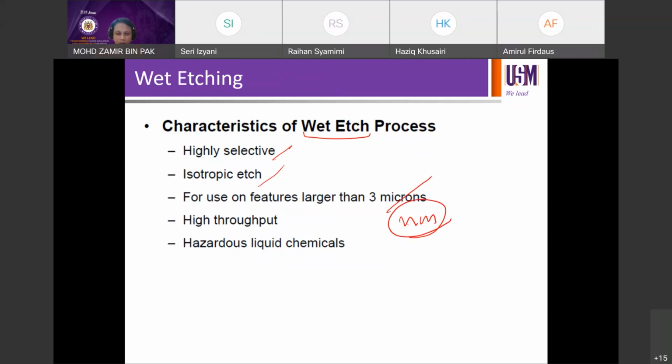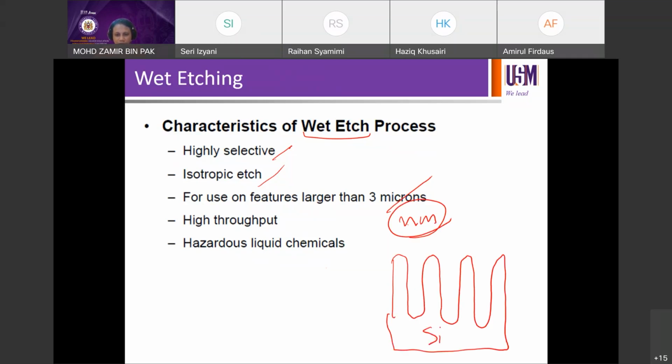For example, our black silicon research produces nanowires like this. The nanowire is silicon, so it comes from the silicon wafer. We just etch into it. So this width is about 100 nano. And the height can be up to a micron. Typically, we do 500 nano, more or less. So what is the aspect ratio for this case?